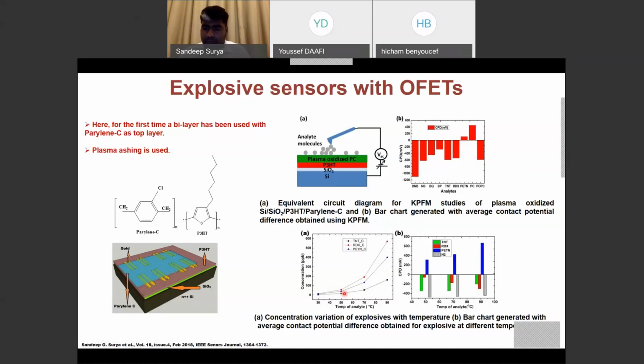Since these are materials with tremendous low vapor pressures, we need enough temperature to increase the emanation of the molecules. So they were heated up to 90 without any shock. We need to be careful. And the concentrations were increased to around 800 ppb.